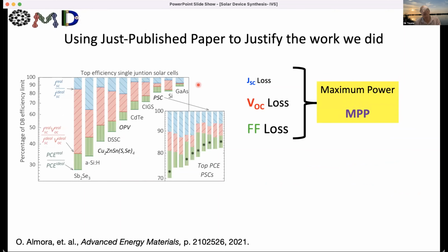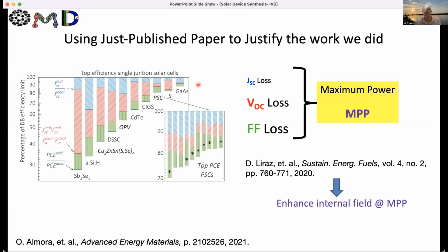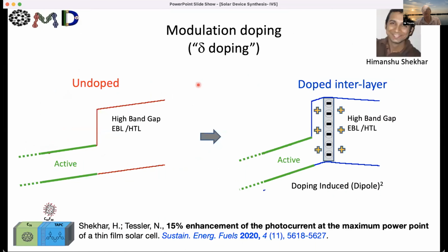So looking only at this short circuit current, VOC or fill factor separately doesn't always help you find the right solution. And really we focused on that point, and this is where Himanshu came into the game. And he managed to introduce a new device structure, which is demonstrated here for a bilayer device.